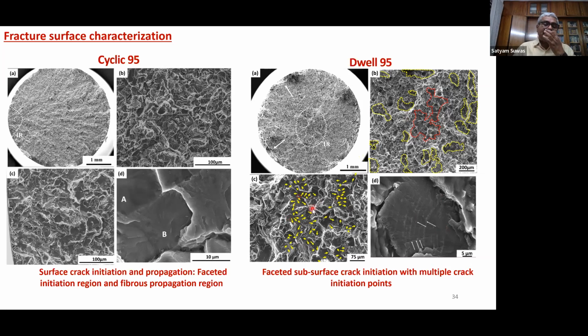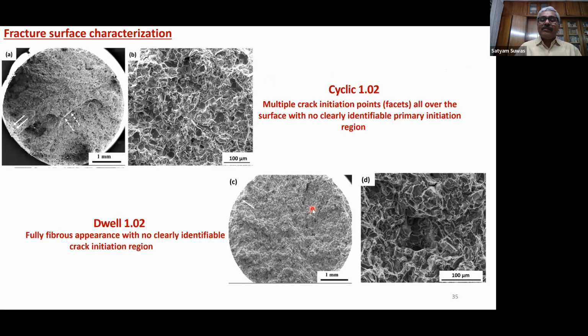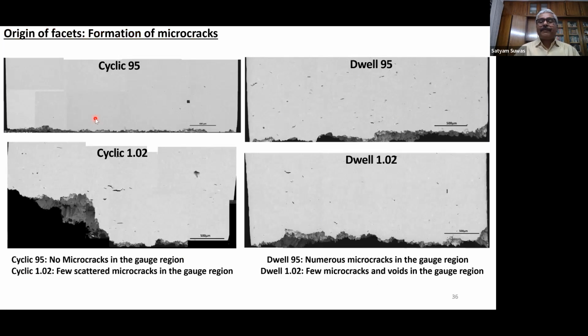So obviously, for the same amount of loading stress, the damage is more in the dwell fatigue loading condition. And a similar situation we could see for higher loaded samples. And here you could see the fracture surface. In this case, in fact, if we take the dwell fatigue samples with higher load, it's so fibrous that we couldn't identify the crack initiation regions. In this case also, it was very difficult to see. But this is for sure that there is a difference.